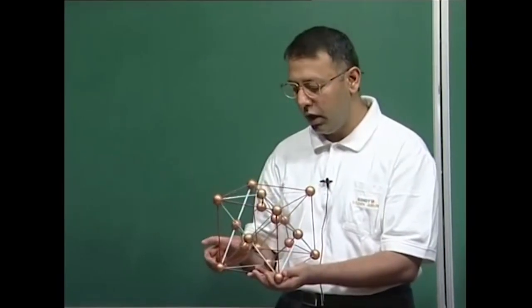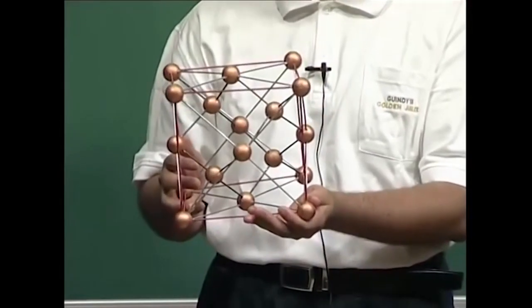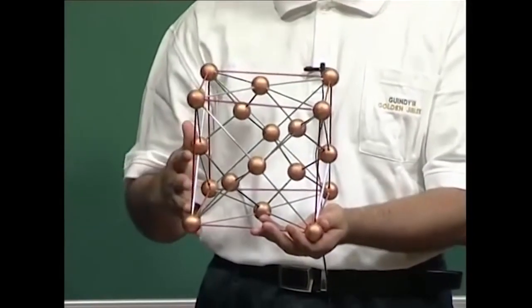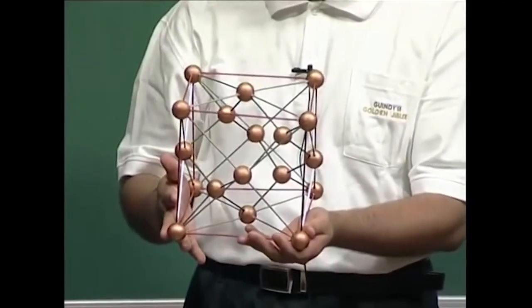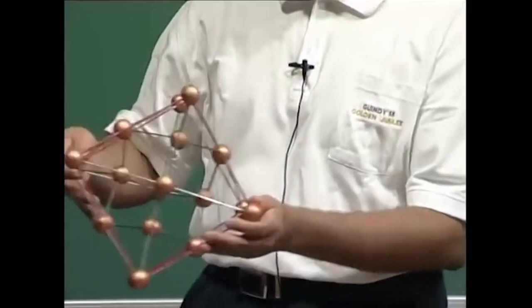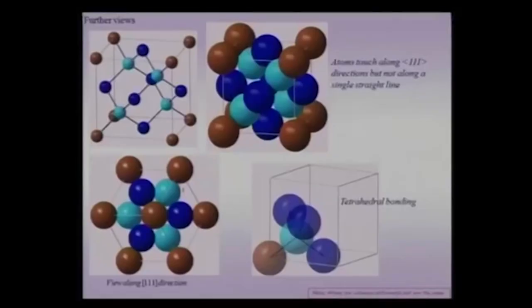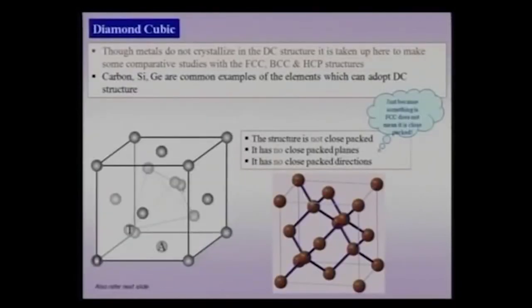For a carbon diamond structure, one atom is at (0,0,0) and another at (¼,¼,¼). Therefore there are eight atoms in a single unit cell. Four of these atoms are on the outer side of the unit cell and four are contained within, and those four themselves form a tetrahedron. Let us see that tetrahedron — the four carbons inside the unit cell — outlined here. This tetrahedron, when viewed from above, has only twofold symmetry or a four-bar roto-inversion symmetry.